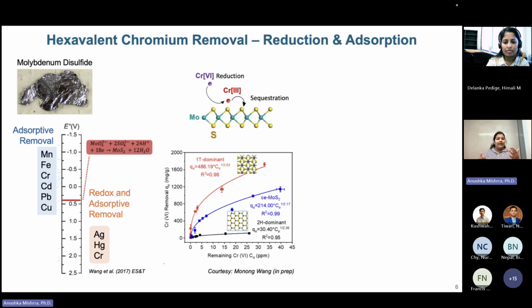There are different phases of molybdenum disulfide that interact differently. For example, the red curve is the 1T dominant phase of MoS2 that undergoes the redox process. There's another phase called 2H which undergoes adsorption - it just removes chromium 6 through adsorption without transforming it to chromium 3. We're interested in looking at one of these phases and how we can remove the toxicity associated with chromium 6 during treatment.